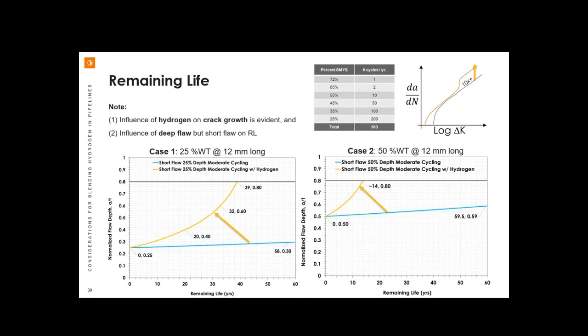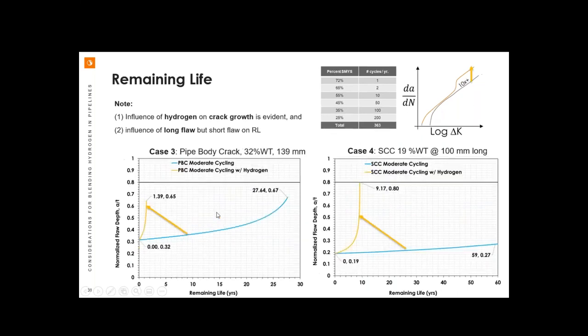Okay, well, those are for our initial crack sizes, but what about how these features perform over time? Christian told you about how introducing any amount of hydrogen, even very low amounts of partial pressure, makes its way into the microstructure and finds its way to crack tips, and that results in almost an order of magnitude increase in crack growth rate. And that's what we see here on these graphs. We see that we have this blue line indicating the remaining life in air for the 2 features, 25 and 50% deep at just about half an inch, and how significantly they are influenced by that new crack growth rate.